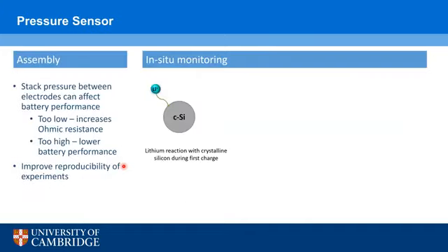And so in our project, we would like to integrate a pressure sensor into this with two main aims. The first would be to try and improve the reproducibility of the experiments, because when you put together these three-electrode cells, you typically have a plunger or some kind of pressure plunger essentially to apply pressure between the anode and cathode.